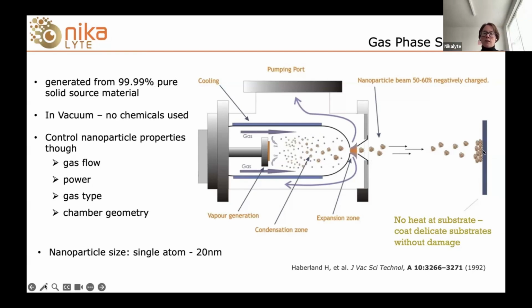So at the substrate, the nanoparticles are formed into whatever structure you've made them be inside their aggregation zone, and they land very softly with very low energy of just a few eV onto your surface. One of the most important features of this technique is that because they land with so little energy, it's possible to coat very, very delicate substrates such as graphene or membranes for catalysis, or plastics, or basically anything that can go in a vacuum chamber can be coated.